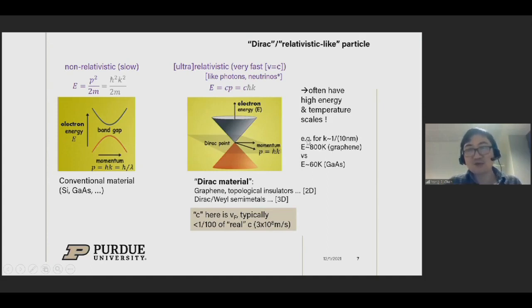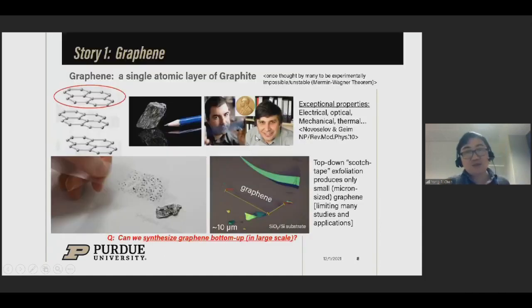For example, the electronic kinetic energy scale for these relativistic-like electrons in graphene or topological insulators can, for a typical electronic wavelength, be very high, on a scale of hundreds or even 1,000 Kelvin, at least an order of magnitude higher than the kinetic energy of electrons in semiconductors such as gallium arsenide. So that's something interesting to keep in mind, because this means you may have a chance to observe interesting quantum behavior that might be more difficult to observe, now at a much higher temperature scale, potentially even room temperature. So let's start